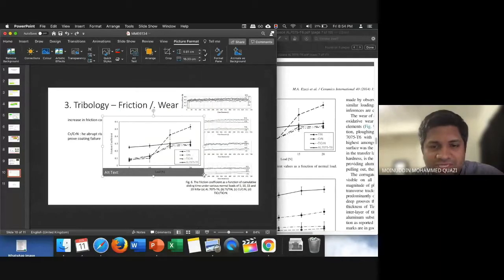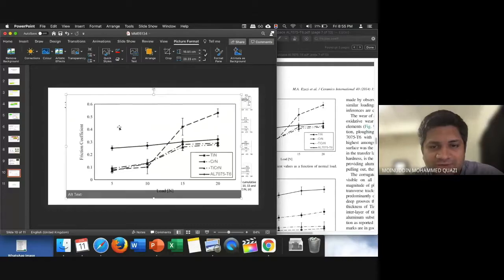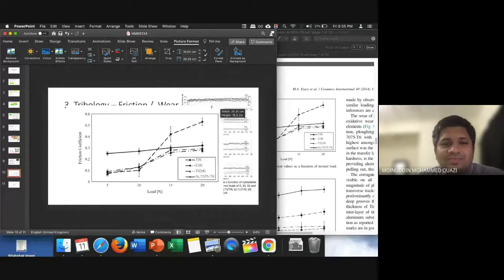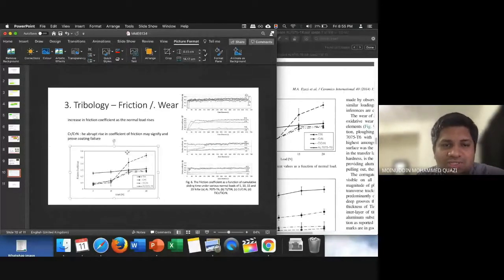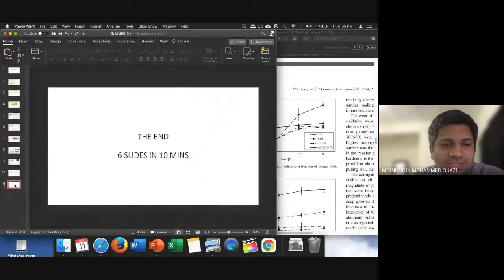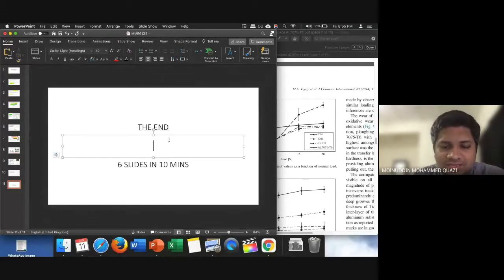And here you can see that you've got 3 coatings and 1 substrate. For the titanium nitride coating, the friction coefficient is very high. For chromium nitride, it is one of the lowest. And for titanium chromium nitride, it is the lowest. So these are some important data that you can recover from the table. That's it. No need to do any conclusion. Okay, so this is the end of your slides. Maybe you can write here just the end and one conclusion from the paper, a one-line conclusion.